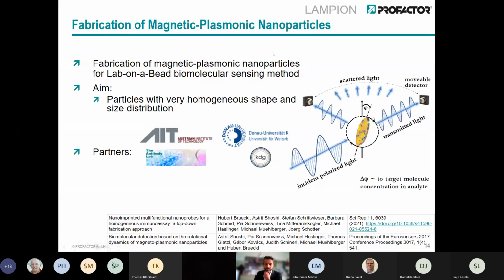A second example, a more recent project where we used a very similar process, was on the fabrication of magnetic plasmonic nanoparticles for biomolecular sensing. The sensing principle is briefly sketched here. So we have particles which are functionalized on the surface. And if the biomolecule that you want to detect is in the solution, it attaches to the surface, and the rotation of this particle in an external magnetic field is changed. And this can be detected using optical means. And the challenge here is to have these magnetic and plasmonic nanoparticles and to have a very narrow size distribution of these particles. And we decided to use nanoimprint lithography to fabricate those particles.